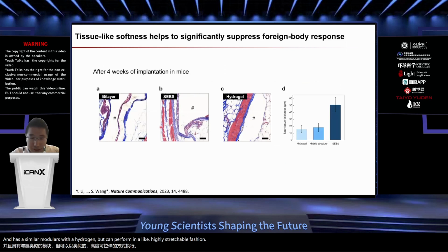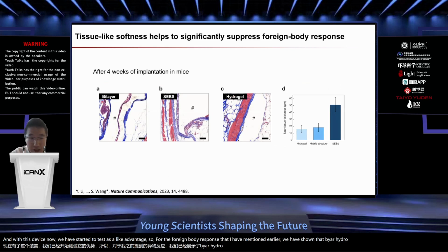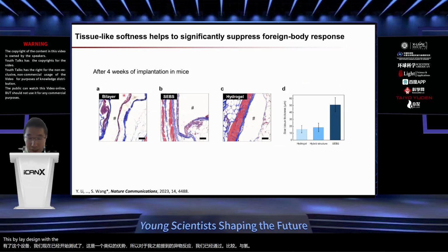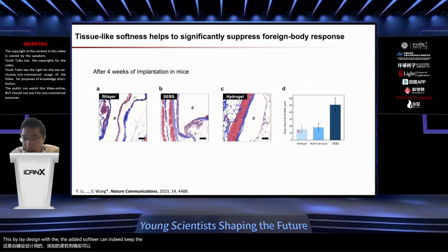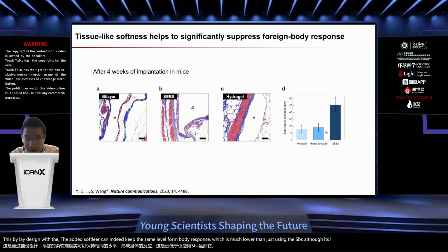And with this device, now we have started to test its advantages. For the foreign body response that I mentioned earlier, we have shown that by comparing with hydrogel, this bilayer design with the added soft interlayer can indeed keep the same level of foreign body response, which is much lower than just using SEBS, although it's an elastomer, but with higher modulus as a substrate for the device.